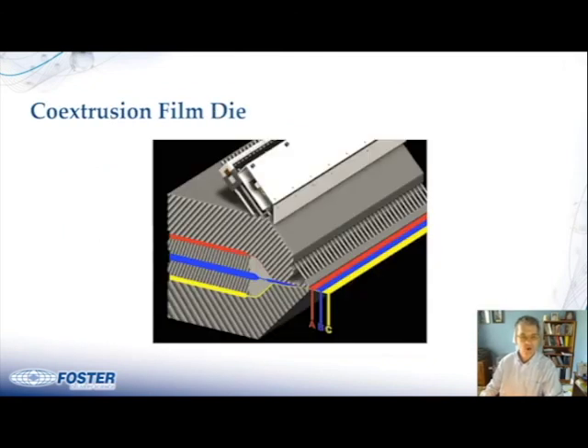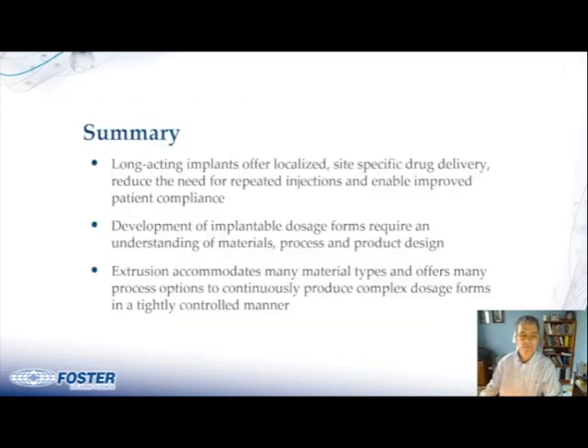And here's a co-extrusion die. In this case, you'd have 3 layers, and this shows a cross section of the flow channels where the 3 different polymers would go through, and then they're formed into a co-extruded film as it exits the machine. So in summary, long-acting implants offer localized, site-specific drug delivery.